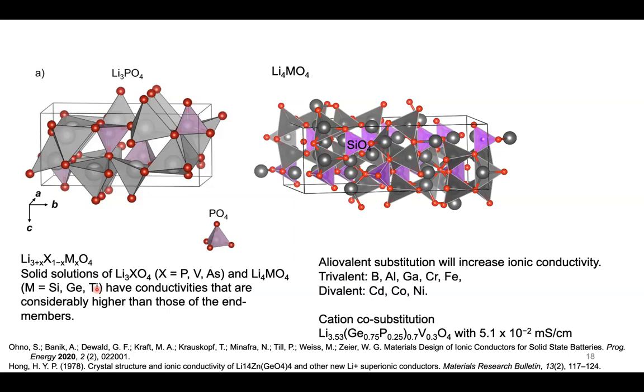People have looked at the end members. They've also looked at the solid solutions of these compositions. And then they've also done things like this sort of cocktail of elements where you have these fractional stoichiometries, and then you can drive up ion conductivity from 10 to the -6 millisiemens per centimeter to 10 to the -2. Okay. Just by basically introducing site disorder and also eventually going away from oxides, opening the diffusion pathway and the bottleneck with substitution of sulfide for the oxygen.